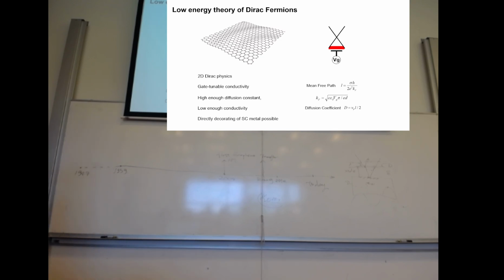The Fermi level can be tuned simply by some kind of capacitance coupling from the gate. And this is a very good example. By this diagram, people can do a lot of calculations. For example, the mean free path can be defined by sigma h over 2 e squared kF, and kF is actually the square root of n pi, where n comes from this capacitive coupling. And the diffusion coefficient can also be obtained.